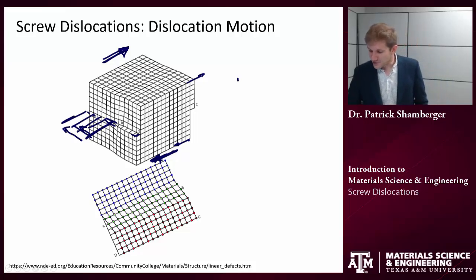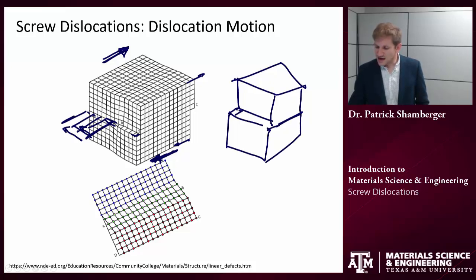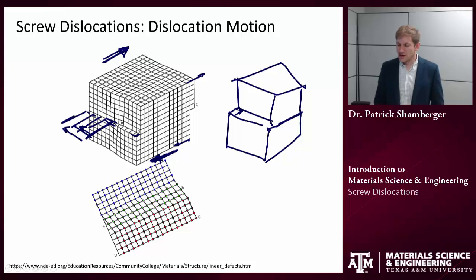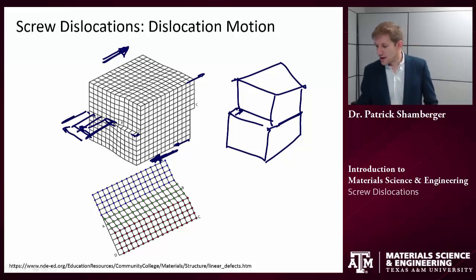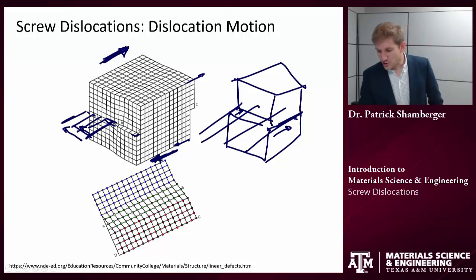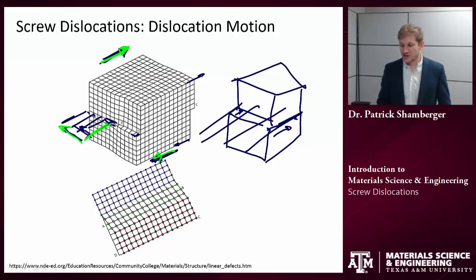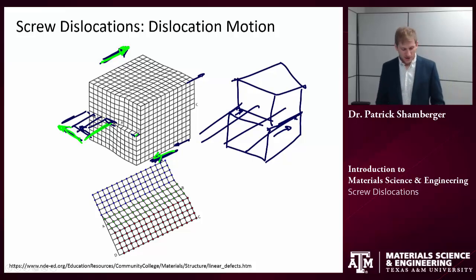The net effect is that after that happens, I now have a volume that is entirely offset by one unit cell. And if I had another screw dislocation pass through that volume — again moving from right to left — it would be offset an additional unit cell. So if I have a particular direction of shear, the dislocation is going to move perpendicular to that direction of shear, and furthermore that direction of motion is also perpendicular to the Burgers vector.